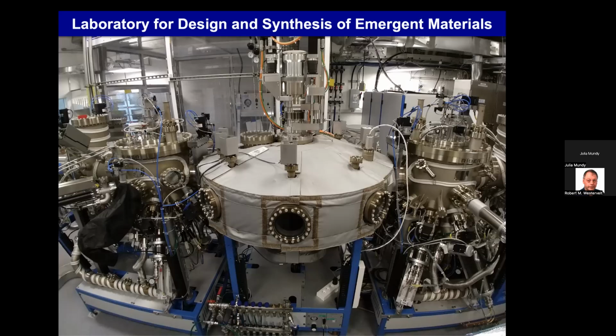So if we think we want to put down 1 atom sheet, we put down 1.01, 1.01, 1.01. You don't notice until like 50 atoms layer, and then, oh shoot, you have an extra layer of something like that. So most of the time when things vary based on thickness, sometimes it's fundamental physics, but sometimes it's just kind of accumulation of defects or something. So you just have to be more precise to get things out of it.